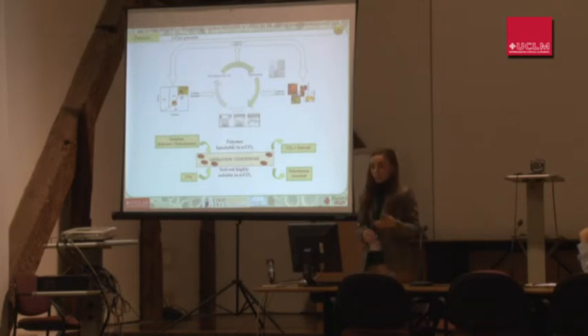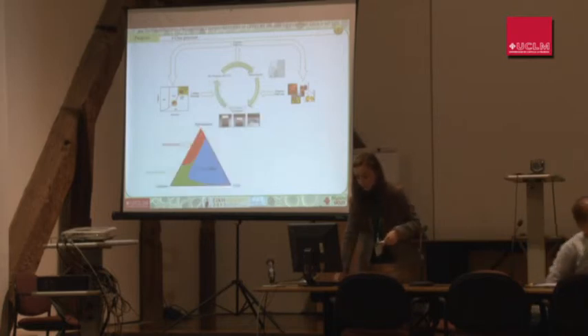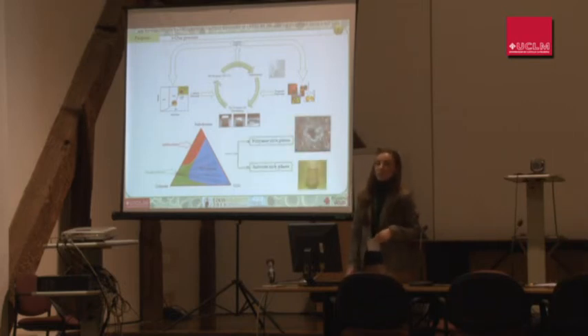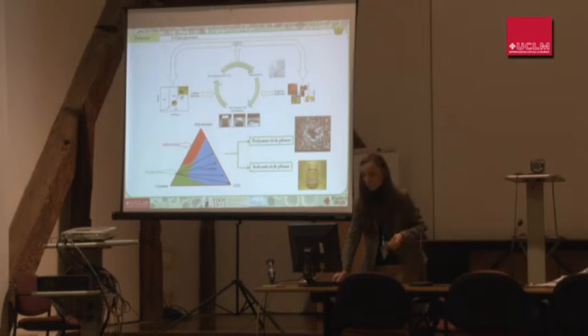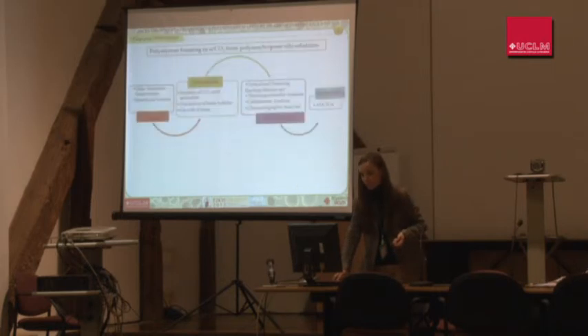Thus, when a solution of the solvent and the polystyrene is contacted with the carbon dioxide, the high solubility of the terpene oil and the total insolubility of the polymer will produce the phase separation, giving recycled polystyrene and a side stream with the carbon dioxide and the solvent. The carbon dioxide will be used not only to induce the phase separation, but also to promote the foaming of the polymer and to get the microcellular foams.